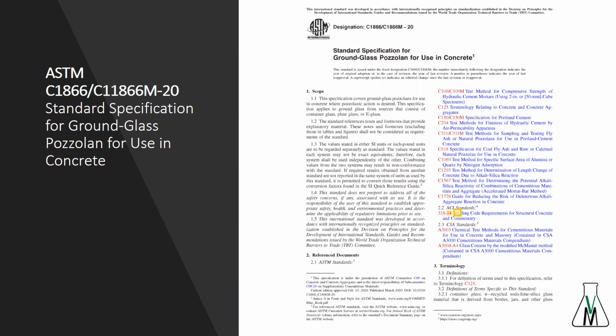Slag is a little bit different because when you add water to slag by itself, it's cementitious, but it also undergoes the pozzolanic reactions. So all of those are great materials, and they're available in very large quantities. The issue with glass is that it is available widely across the United States, but not in concentrated quantities, and it takes quite a bit of beneficiation to clean it up and get it ready for concrete. As sold in concrete, it's about the size of concrete powder, 95% passing 325 mesh, and it's extremely pure. Let's look at the next slide.